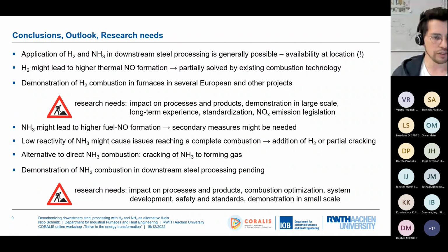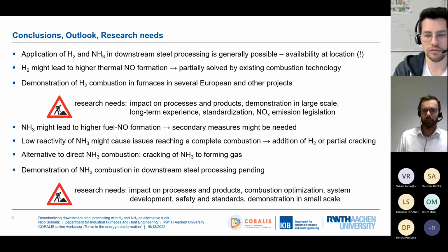Talking about ammonia, it might lead to higher fuel NO formation, and there possibly we will need secondary measures at our furnaces that we have not by now. Additionally, the low reactivity might cause issues reaching a complete combustion, but this could be solved if we add some hydrogen or partial cracking. An alternative could be the cracking of an ammonia to forming gas.